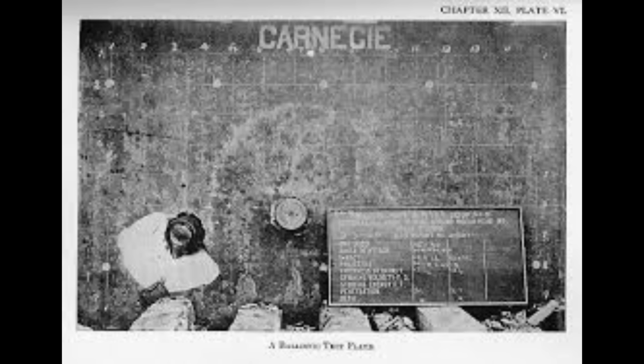The test plate went to the firing range. Zanotti watched through reinforced glass as the test crew loaded a 40mm AP projectile into the test gun. 500 meters range. The gun fired. The projectile struck the plate dead center, producing a distinctive metallic clang. The plate rang like a bell, a good sign, indicating energy absorption rather than brittle fracture.